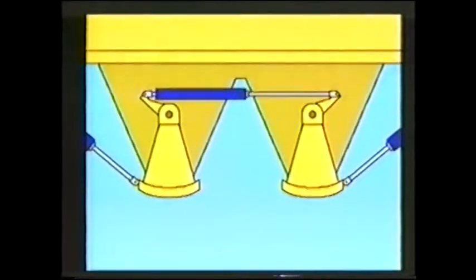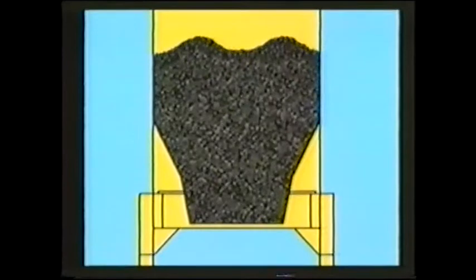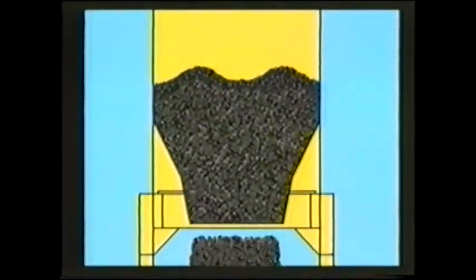At the bottom of the silo, the discharge is also divided into two sections. The walls are very steep, and discharge gates are 6 feet wide. These openings are 90 degrees opposed to the openings in the slug feeder. We can see this clearly from a top view. The red slots are in the slug feeder, and the blue slots are in the bottom of the silo. So you can see that at no time is the material fed down the center line of the silo. Therefore, segregation is virtually eliminated. As the gates are opened, the material mass flows so that the even blend is not disturbed.